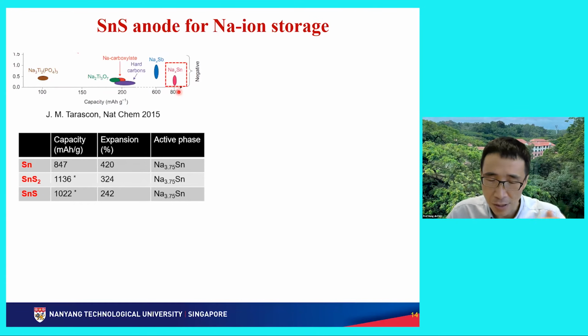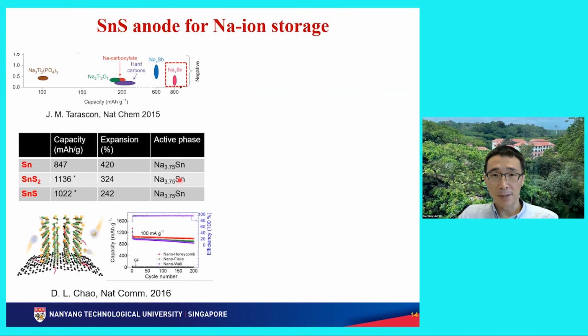Okay, make the electrode even thinner. The commercial material I mentioned just now is mainly hard carbon here. Okay, 200. But if you replace it with tin, it can be more than 800. But the problem of tin, which is a typical phenomenon for all alloy type, is the high volume expansion. Therefore, after a few cycles, they pulverize, they scatter, okay? They break into small particles and then cause a failure of the batteries.